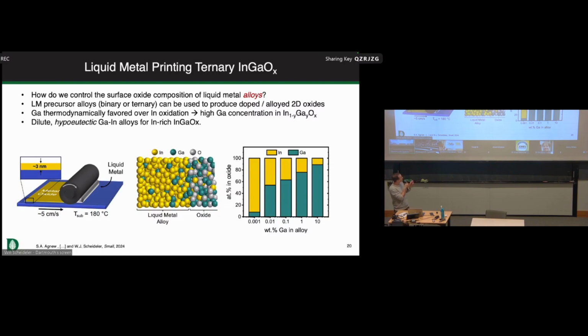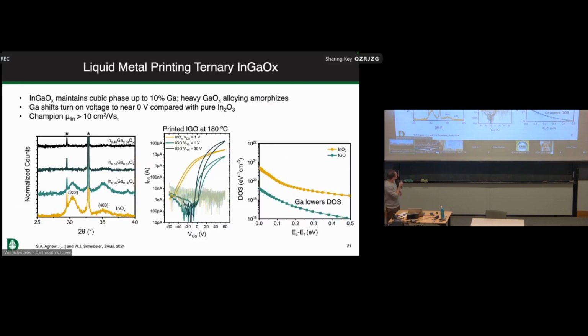And you can then form alloys that are still semiconducting rather than purely insulating, but give us the characteristics that we would like. We can quantify this in a couple of ways. One, we can measure the transfer characteristics. The lower intrinsic carrier concentration, because of the lower oxygen vacancies, gives us the ability to put the on voltage for these devices closer to zero. For a lot of thin film circuits, if you have a display or another sensor, you want to be able to operate with a unipolar power supply or unipolar circuits. Having a turn on voltage near zero gives us the ability to do that.